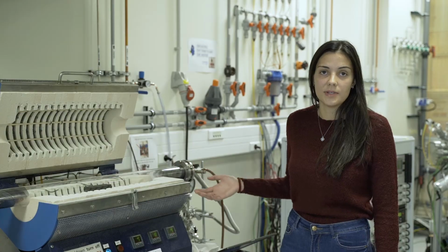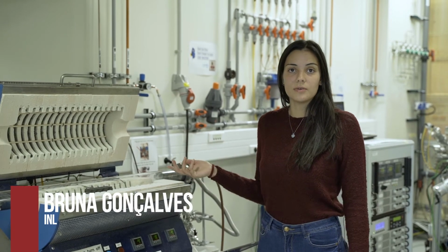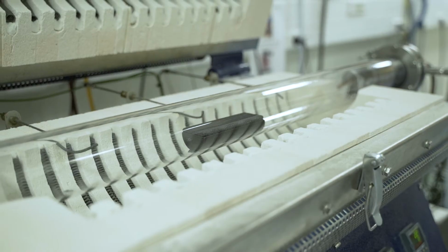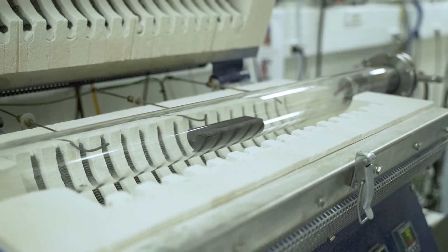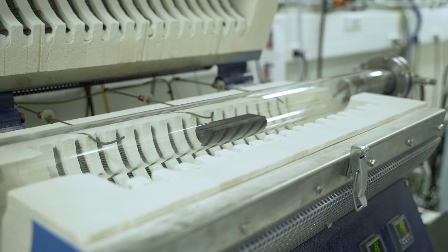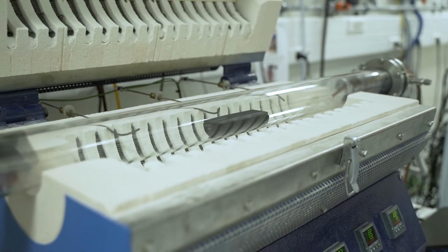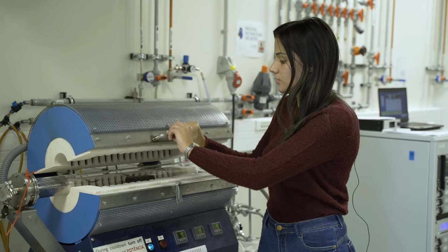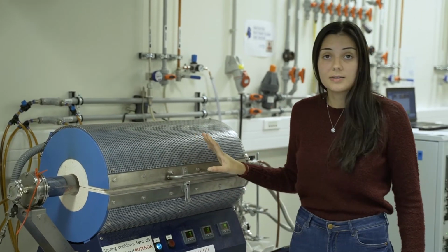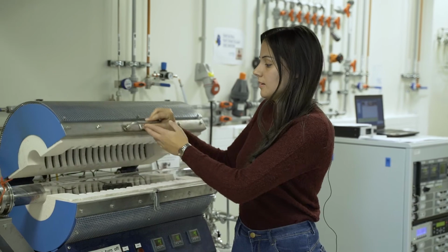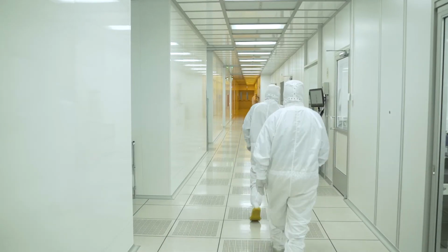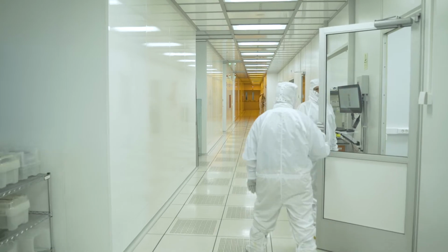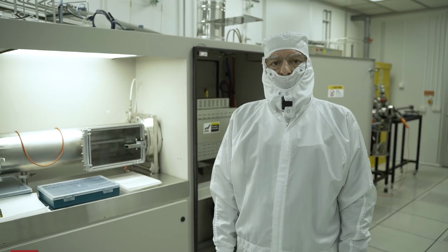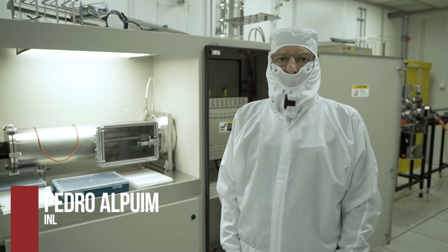Here we do the CVD technique, where we use molybdenum samples to deposit selenium and form the final crystal, molybdenum diselenide. Inside this graphite box, we put the samples. Then, by the use of an inert flow, we deposit the selenium and form the final crystal. Here, we insert the temperature that we need, we close the furnace, we wait, then we open it to cool it down, and it's ready.